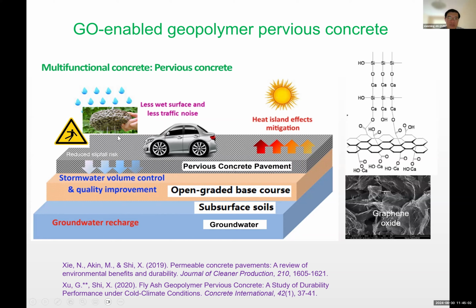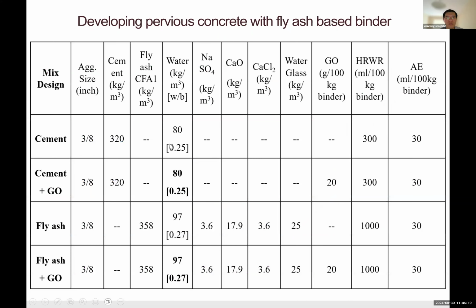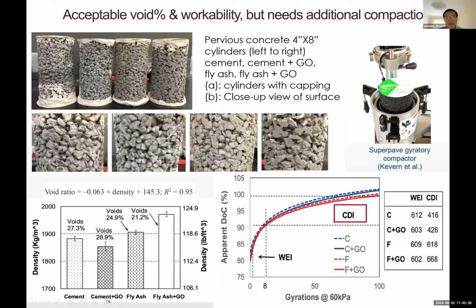One thing that's not very green is we still use cement, right? So that's where we're trying to replace the cement. So again, here we develop 4 types of mix designs of pervious concrete. One uses cement, one uses cement with the graphene oxide, one uses fly ash, one uses ash plus the graphene oxide. Typically, the design is different than in conventional concrete by reducing or eliminating the use of fine aggregate. So you've got the built-in ability to infiltrate rainwater. So the gist of the story is that if you look at the density, the fly ash ones are somewhat denser versus the cement-based ones, but they're still pretty reasonable. And then their void ratio is in the range of what we would define as pervious concrete. And in terms of compactability or workability, they're very similar.